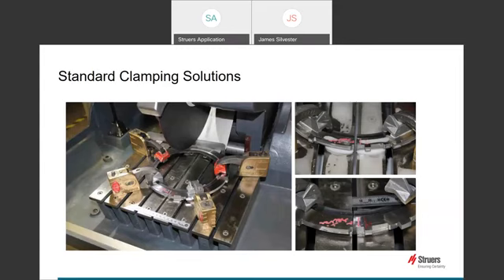Care should be taken to ensure fragile specimens are supported and protected by clamping jaw faces. The use of rubber matting between clamp jaws or feet and the sample can give a few benefits, including cushioning from a hard face, flowing around a sample face that may not be uniform, and giving increased friction to prevent movement. Shaped and grooved jaws and feet, along with custom-made jigs for special applications, can be used to good effect when setting up a cut. The more often a particular cut takes place, the more we would lean towards setting up a jig for repeatability. Obviously, we can't cover everything in this webinar, so we've just picked several examples that either often get raised with us here in applications, or were noteworthy as something that gave us cause to find a solution to a tricky problem.